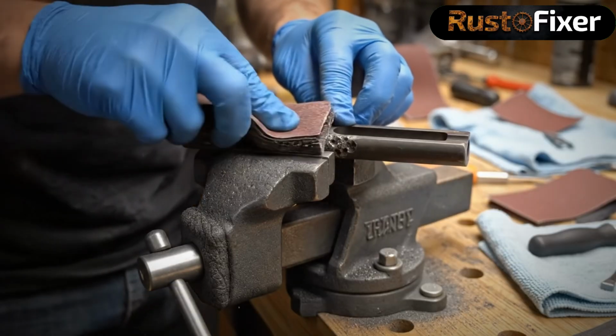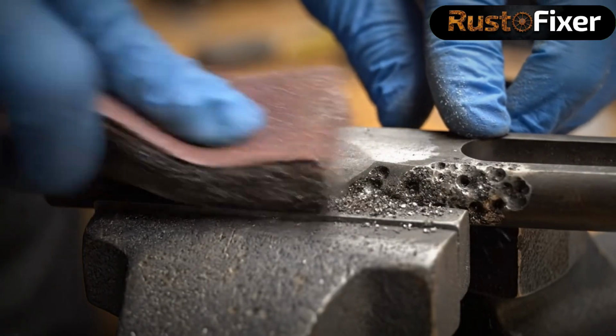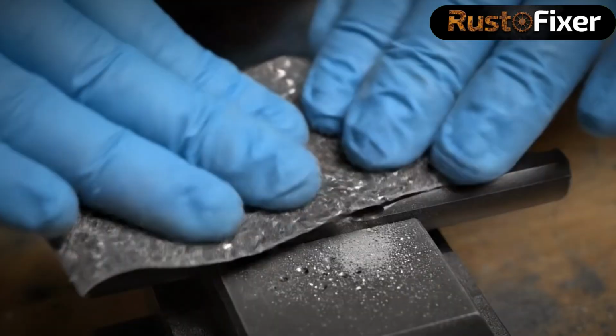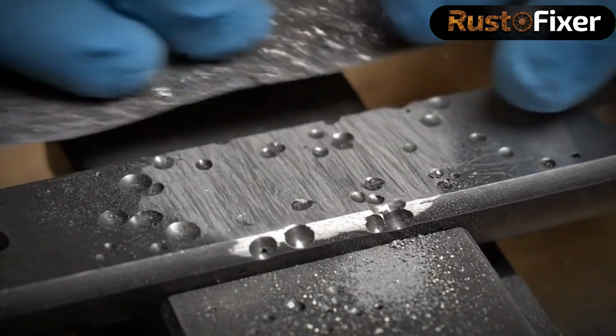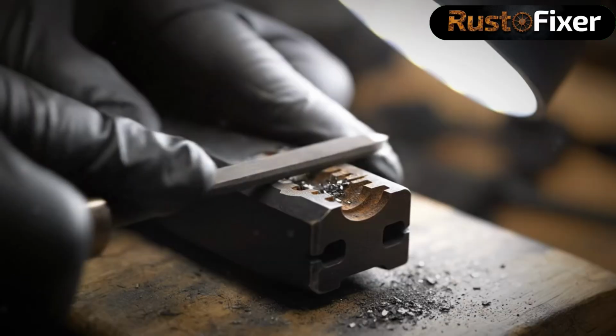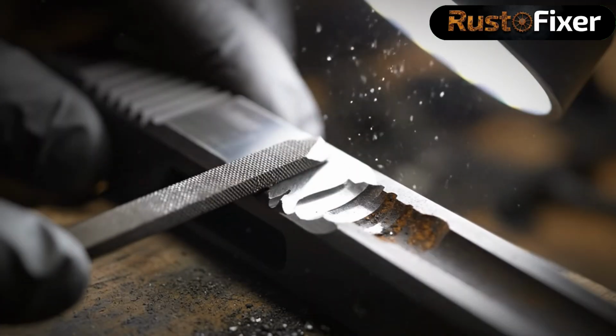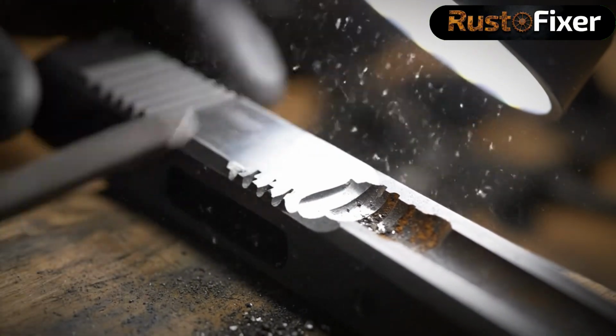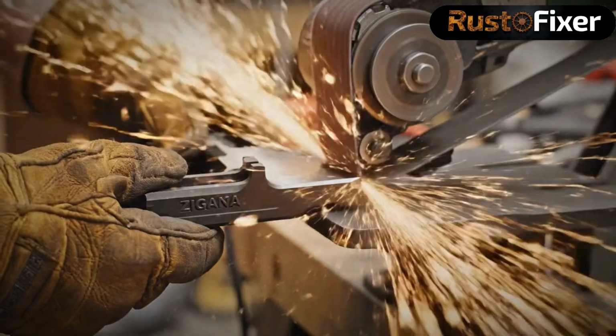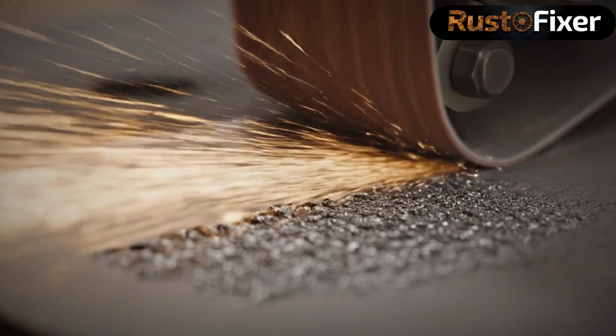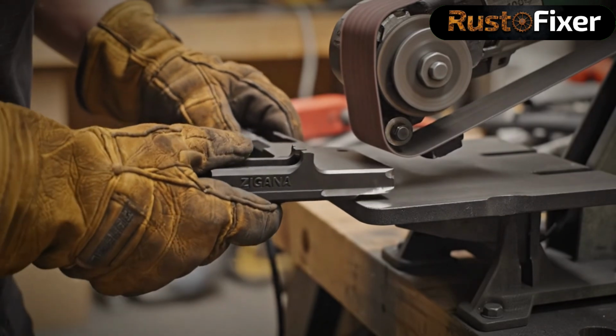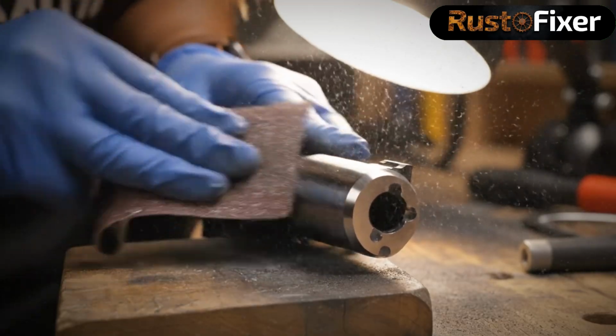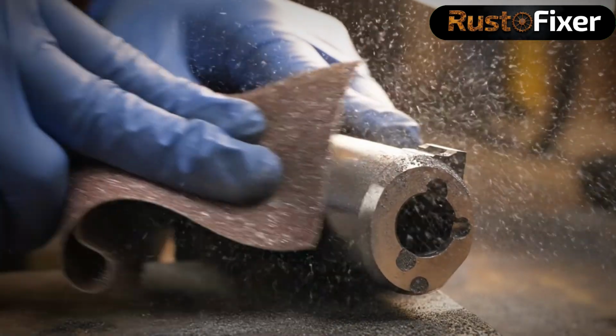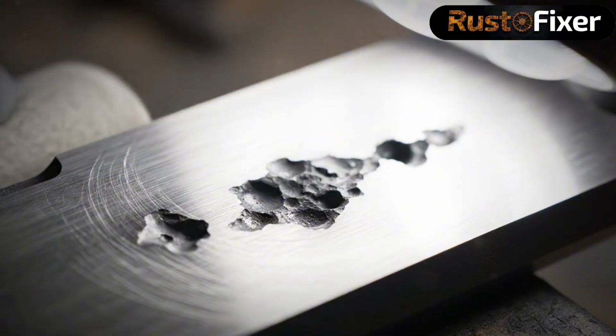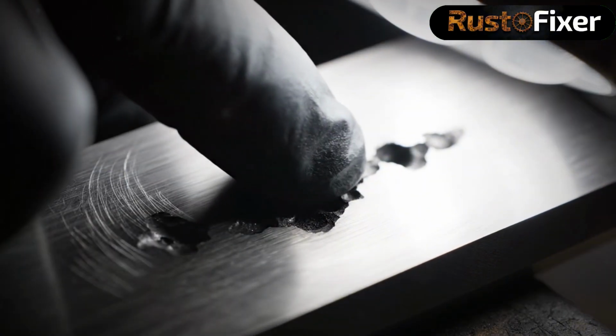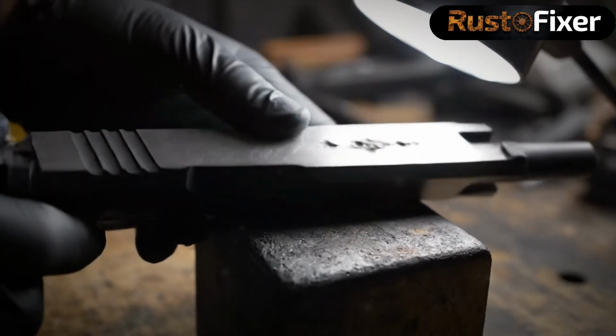The transformation of the heavily pitted Zigana slide begins with aggressive surface preparation. Coarse abrasives are used first. The slide's serrations, once obscured by rust, are carefully worked with small files and shaped abrasive tools. For the flat sides of the slide, a belt sander with a coarse belt is carefully employed. This removes material quickly and efficiently. Curved surfaces and contours, like the front of the slide and the muzzle area, are hand sanded with coarse grit paper. Deep pits that cannot be completely removed without compromising the slide's structural integrity are accepted as part of its history.